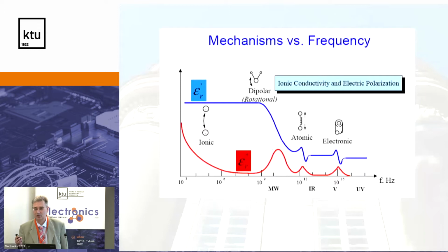So, another issue: then we have a material, any material, a dielectric material or ionic material, because it will also be in the program, a few talks about batteries. So if you look at the frequency range, if we start from the low frequency part, in the low frequency part we usually have conductivity processes. This is a charge transfer, which goes from one contact to another. Then you apply an electric field, and if we have ions or electronic conductivity, we have a conducting material. So resistors or water, ionic liquids, ionic conductors, which are used in batteries, lithium batteries, for example, they have ionic conductivity. So it's one big field